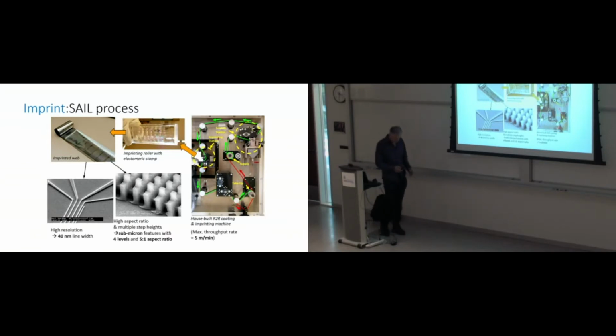See here, I don't know if you can see, but we made a master using a Bosch process where you etch for a little bit, then you passivate and etch. And you see there are little scallops here. Each one of these is a 50 nanometer scallop, and they all get replicated. And you notice the top is actually a little bit bigger, so that's that reentrant thing. So you can make very complicated structures, and the fidelity of replication is very high. So if you want an optical structure or a flow structure or something like that. Now, it's really suited for optical.